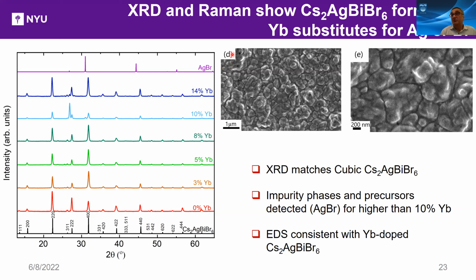So the first thing to establish is that when you do this, the target compound forms and ytterbium substitutes for either silver or bismuth. Here I show SEMs of two different scales, of the films that one gets. They are polycrystalline, and depending on what you might call a grain, they're a few hundred nanometers up to micron in size. The X-ray diffraction matches cubic cesium-2 silver bismuth bromide 6. So here is the simulated structure, and this is the X-ray diffraction pattern of various ytterbium doping levels. The peaks shift very subtly, but we establish the substitution of ytterbium using Raman spectroscopy, actually, not necessarily X-ray diffraction.